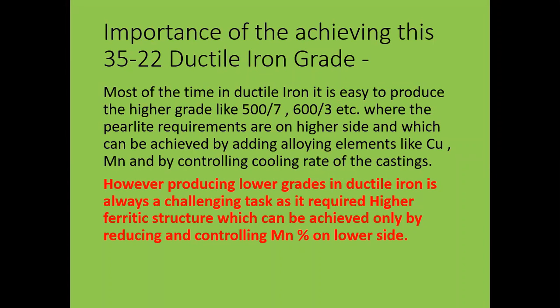Importance of achieving this 35 by 22 ductile iron grade. Most of the time in ductile iron it is easy to produce the higher grades like 500 by 7, 600 by 3 grades, where the pearlite requirements are on the higher side and which can be achieved by adding alloying elements like copper, manganese, and controlling the cooling rate of the casting. So it is very easy to produce higher ductile iron grades.